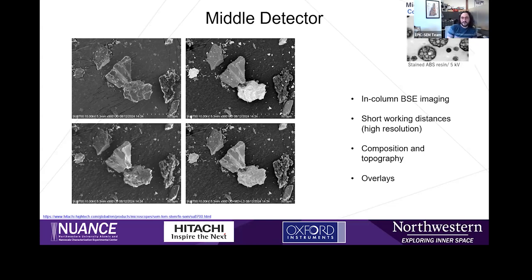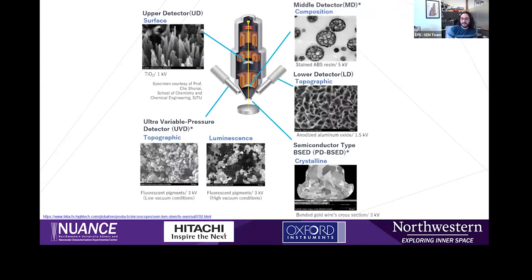It combines the best qualities of an upper, lower, and backscatter detector into one that gives a great compositional and topographical high-res image. And on top of all that, the 8700 lets you overlay all 3 signals into one mixed signal image, which you can see in the bottom right, to just get all that info into one shot. And each signal is adjustable, so you can play around with it to really optimize your data. So that was a good introduction to the middle detector.